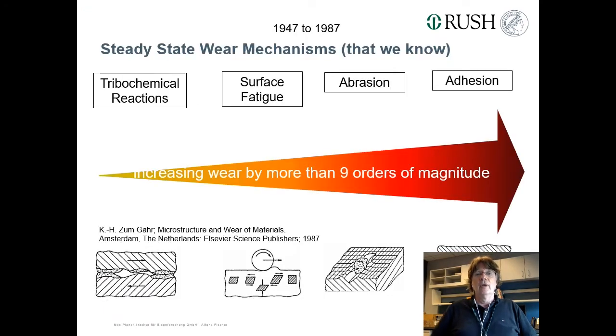The only thing we know is that when we just concentrate on the four main wear mechanisms, which more or less is state of science from 1947 to 1987, so roughly 40 years of basic and applied research, we know that the wear rates might increase by 9 orders of magnitude. This is 1 billion, you know. It's a question whether you part lasts one day or a billion days. That's quite interesting for industry.